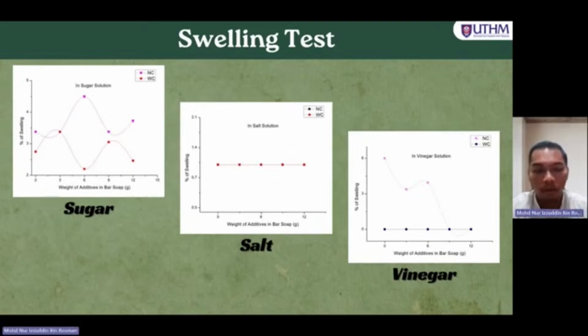But for the salt, all the samples show a similar trend, where the percent of swelling is around 1%. This shows that salt may create a more gentle environment for maintaining the composition of the bar soap formula.